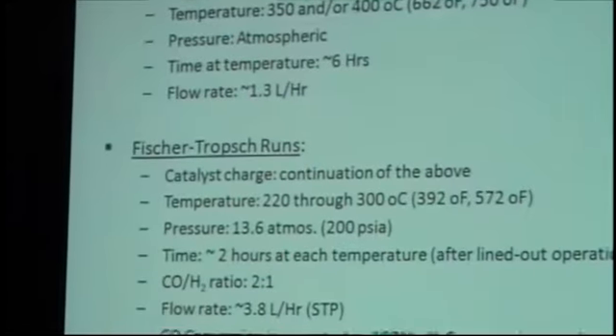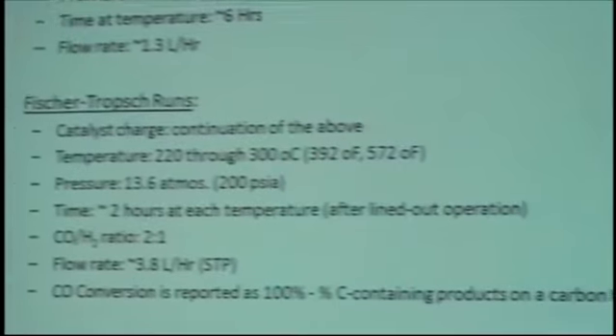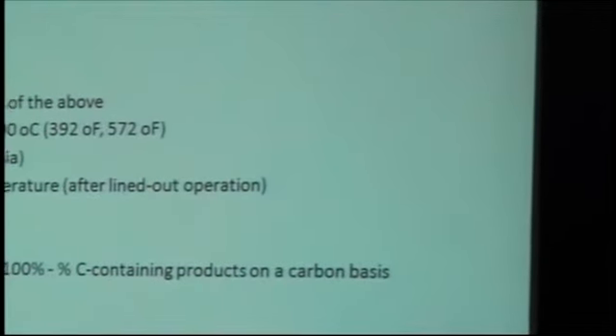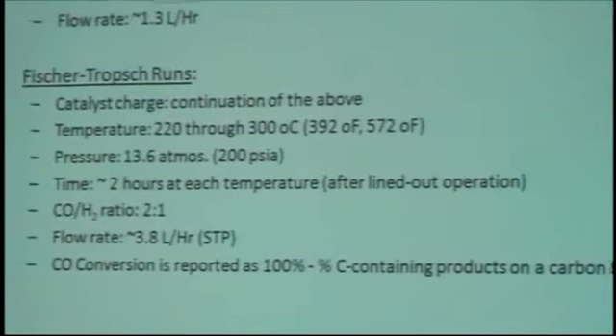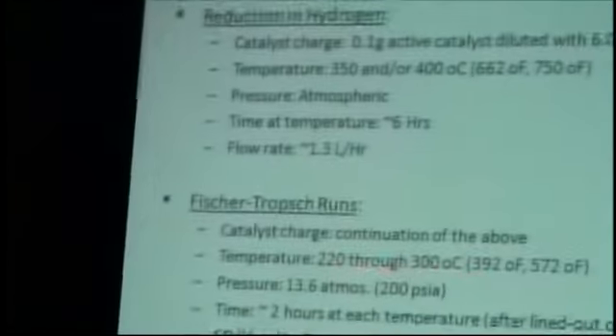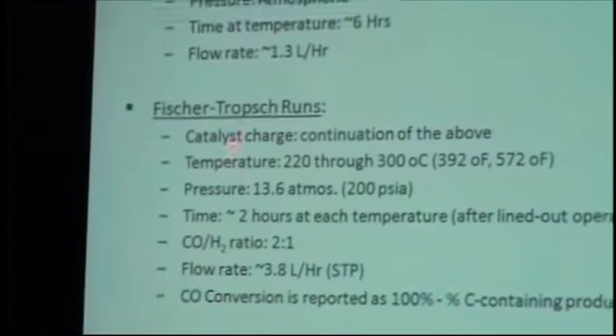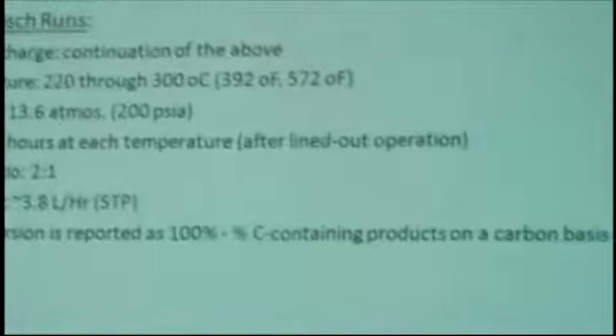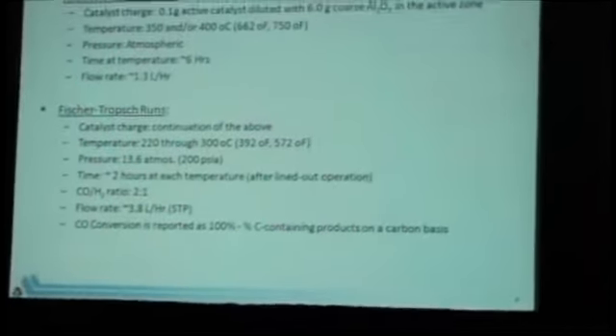This was followed up with Fischer-Tropsch runs in that same reactor, of course cooling overnight to get down to the desired reaction temperature. Temperatures were on the high side, you might say, for Fischer-Tropsch reactions: 220 through about 300 degrees C, at 13.6 atmospheres, 200 pounds pressure. It takes time to heat up to the reaction temperature. The reason for having 2 receivers is to collect the gas samples and let the system line out. We held it for 2 hours at any individual temperature. The CO to hydrogen ratio was nominally 2:1, and the flow rate is fairly high.